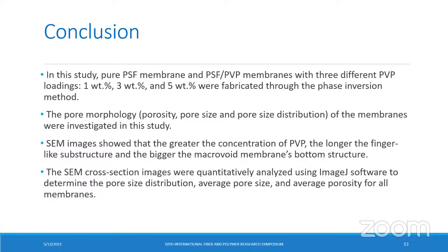The SEM images showed that the greater the concentration of PVP, the longer the finger-like substructure, and the bigger the macrovoid in the membrane's bottom structure. The SEM cross-section images were quantitatively analyzed using ImageJ software to determine the pore size distribution, average porosity, and average pore size for all membranes. And all the reported data were within the acceptable standard deviation.